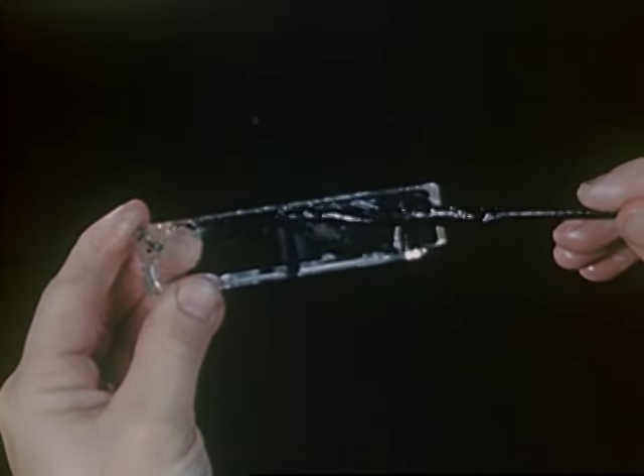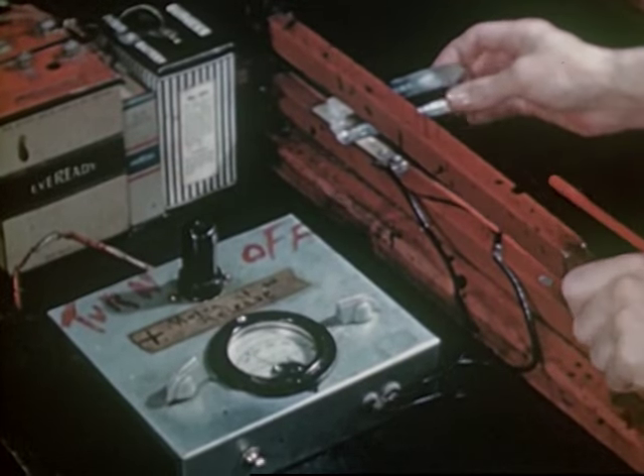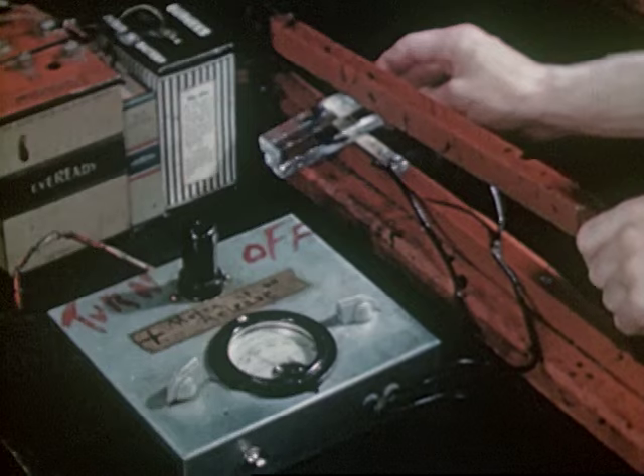As a first step, we need to identify the electrically negative and positive faces of the quartz bar. This is done by squeezing it gently under a lever arm and measuring the electrical charge on a vacuum tube voltmeter.